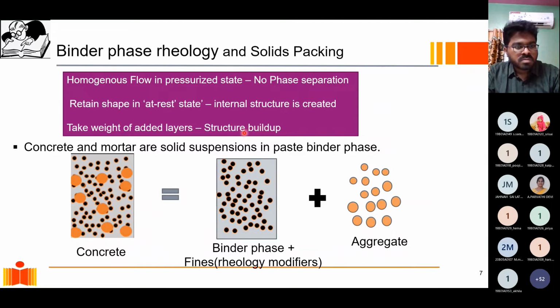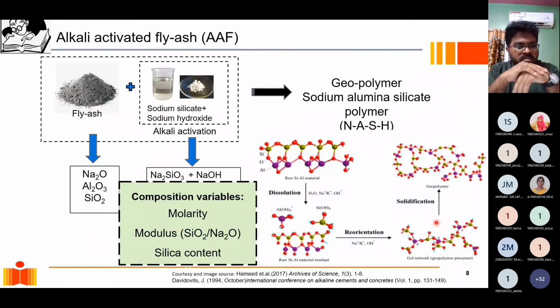It's not setting or strength gain, it is buildup. The material itself still is in a fluid state. That means it is still not set, but it has enough internal resistance structure that I can keep adding layers. So that's what we are looking to engineer in this material. And to engineer the material, we have to basically look at this binder phase rheology. We have to understand what the paste behaves like and what happens when we add aggregate to it.